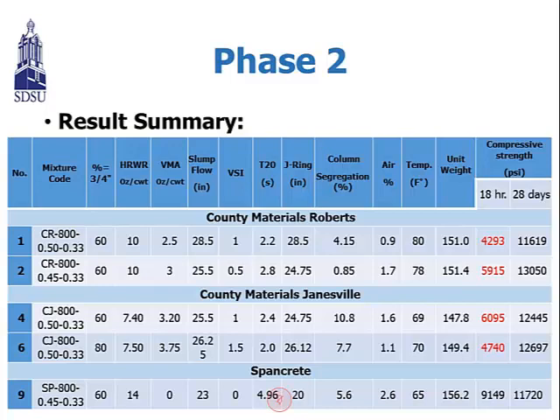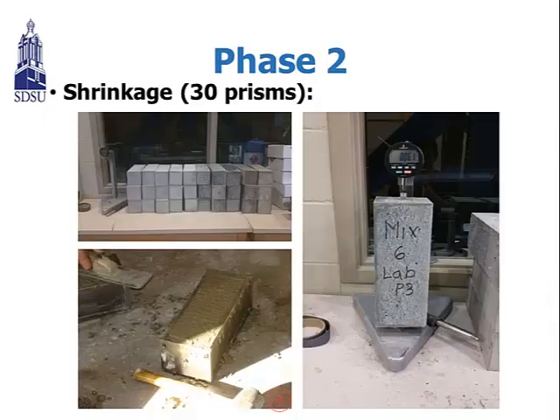Spancrete, on the other hand, has very carefully placed and cured the concrete, and you can see the higher compressive strength at 18 hours. And also you can see the shrinkage prisms. There are two sets of the shrinkage prisms, one set from the plant and the other one made at SDSU facilities. When you see the picture, the white one is the plant and the little bit darker 15 prisms were made at SDSU. And we compare the difference between the shrinkage strain fabricated from the plant and the SDSU facilities.